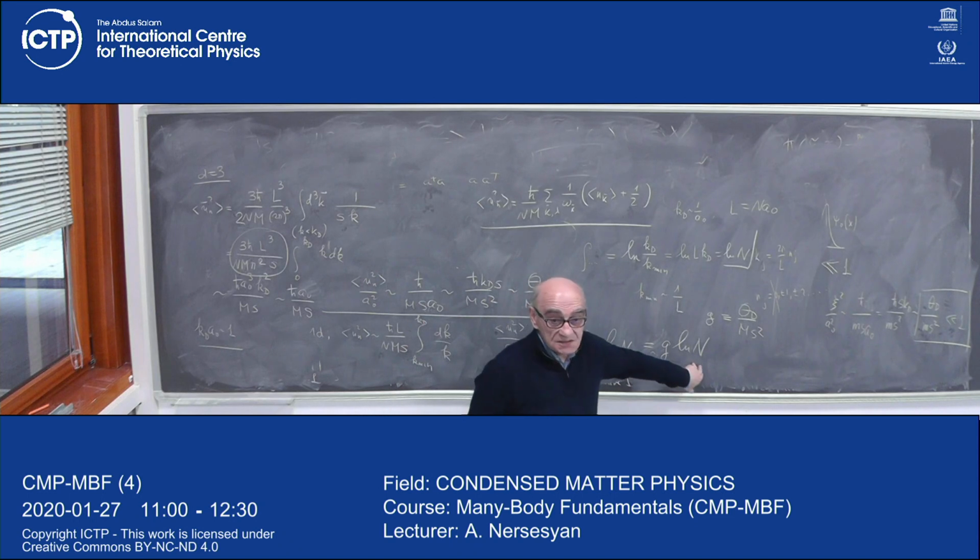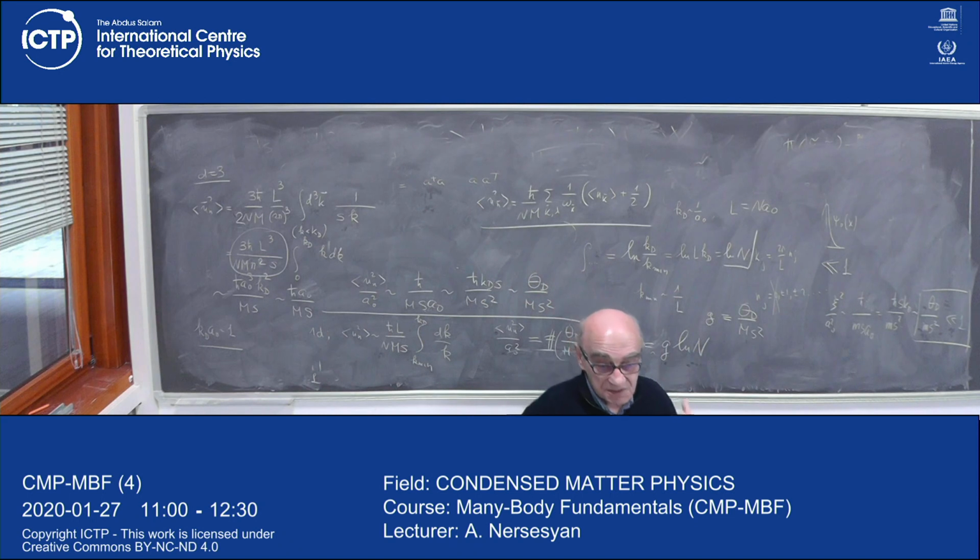And it turns out that if I, quite consistently, as a consistent theoretical physicist, for this non-extensive quantity set n equal to infinity, in other words, go to the thermodynamic limit, I have a divergence. The conclusion is, there are no stable, in the thermodynamic limit, one-dimensional crystals in nature. They simply don't exist.